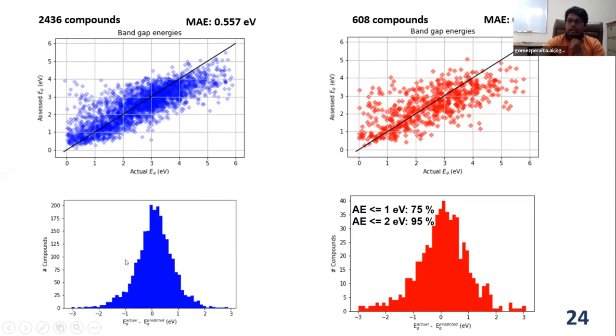Below, you can find the number of compounds against the difference between the band gap calculated by Kim and coworkers and the band gap predicted by the convolutional neural network. And the important thing here is that with the compounds of the test set, 75% of the assessments done by the convolutional neural network had an absolute error below 1 electron volt. And we can say something similar: 95% of the assessments had an absolute error below 2 electron volts. The important thing here is to make this error lower in order to have more accurate predictions.